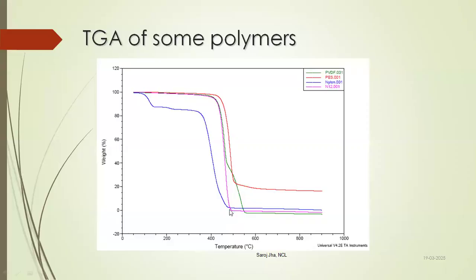So here, if you see on the y-axis, the weight percent remains 0, residue remains at 0, which means that the pink curve is totally degraded. Now let's concentrate on the red curve. The red curve follows a similar pattern to the pink curve, but if you see the residue, it is not 0 residue like the pink curve, but it is giving me 20% residue. It means the TGA shows that the onset is around 425 degrees centigrade, and the material is giving me 20% residue.